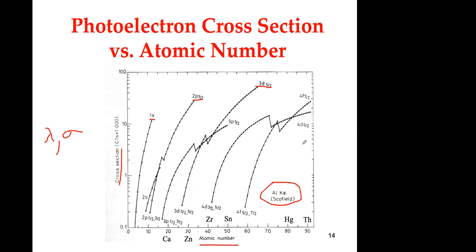So it's another parameter. For example, if you take calcium and zinc, and you look at the 3P1/2, 3P3/2, this appears like here. The value for zinc is up here. So that's probably a factor of 10 in intensity for zinc compared to calcium, and that's a huge change. That means that under the same conditions, and probably the same concentrations of calcium and zinc, the zinc peaks will be higher in intensity compared to calcium.